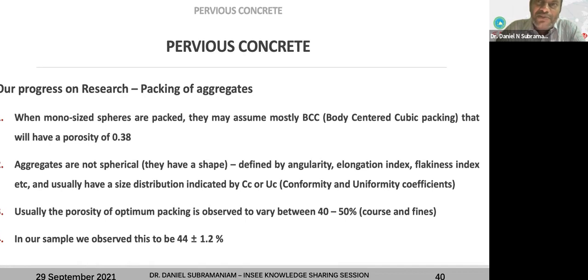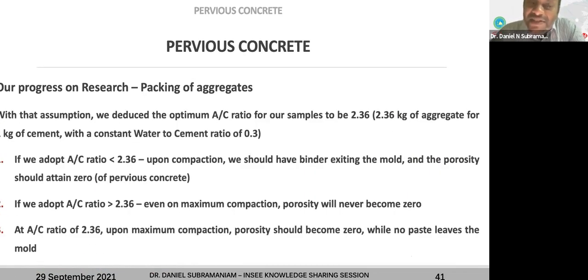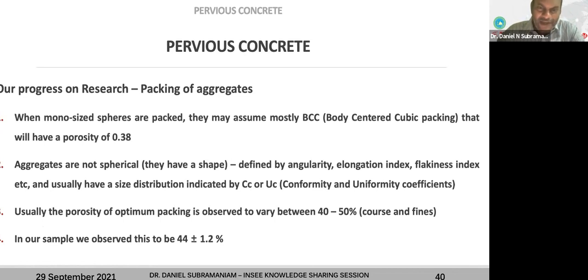So you will never be able to keep all that inside, right? But on the other hand, if you use an aggregate to cement ratio which is more than the optimum, then no matter how much you compact, you are not going to get to zero porosity, right? So that is a concept that we developed.